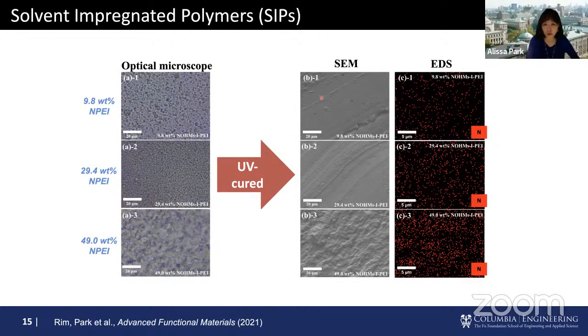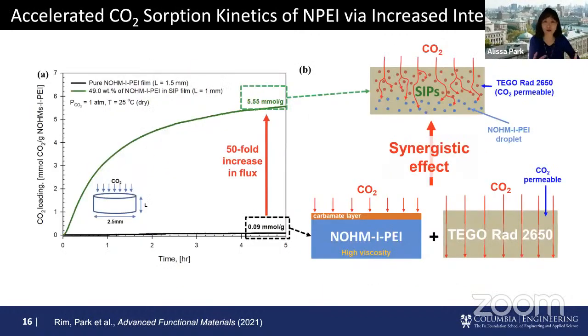But then if you go inside, really zoom in, there's sub-micron droplets of NOHM-I-PEI everywhere. And as you can see in EDS mapping, you see nitrogen everywhere, which is associated with NOHM-I-PEI. And because it was well distributed and very, very tiny droplets, sub-micron droplets, our CO2 capture kinetics were significantly improved further. So it worked really, really well.